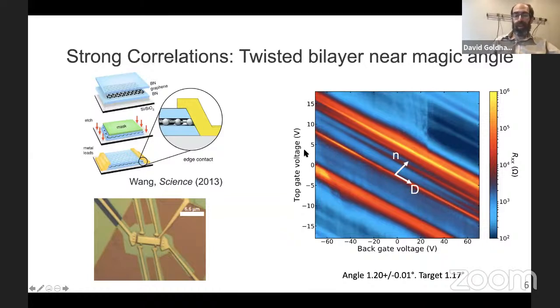And what you can notice is that if you vary the 2 gate voltages in opposite directions, then you're going to stay at the same carrier density in the sheet, but you'll change the electric field, what we call a displacement field, normal to the plane. On the other hand, if we change the 2 gate voltages in the same direction, we'll change the density. And this is a sample that was a little bit above the magic angle, 1.20 degrees, as compared to 1.05 to 1.1. That may seem not very much, but it turns out even hundredths of a degree variation can make a difference in these samples. So let's look a bit more at these measurements and see what we can get out of them.